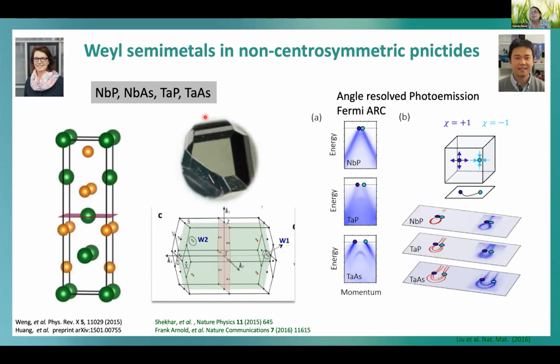So to see this first simple example: it's a family of niobium phosphide, niobium arsenide. They were grown - first there was a prediction on the iridate, but this could not be realized. With this simple material, a tetragonal unit cell, it was possible to realize the Weyl semimetal.